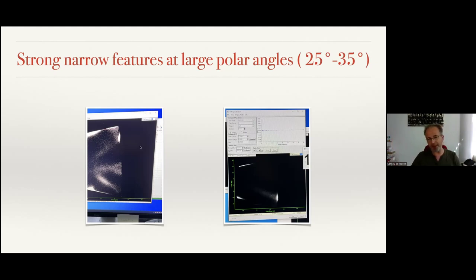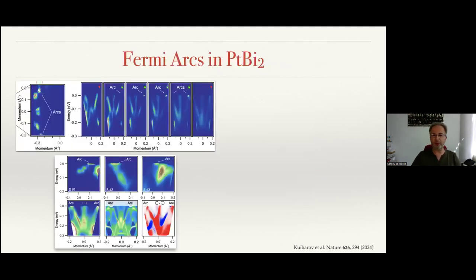immediately seen, but also those which fly away at very different angles. And then we realized, and I show again the screenshots, just the photographs from the laboratory, because this feature which you see here, energy is horizontal and direction is vertical. This is a hemispherical analyzer. This is this unit of information, vertical slice of the onion. And we saw this feature directly on the screen. First, we thought this may be an artifact, and then we had a closer look. This turned out to be exactly the feature caused by arcs.